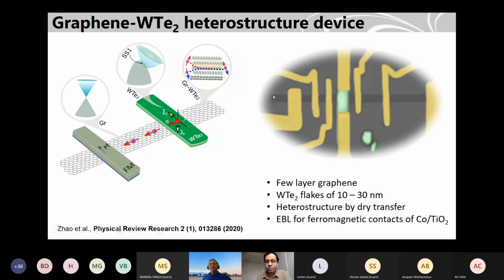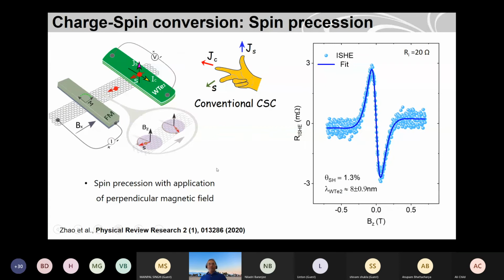Okay, so as you see, the device is here. This is the graphene, then you have tungsten telluride. We have these contacts, both ferromagnets and non-magnetic contacts. So what is the experiment? First, we observe two types of things here, and one is the conventional spin Hall effect. I say conventional charge-spin conversion. CSC means charge-spin conversion: we apply either a charge current or a spin current, and we can convert from one to the other.